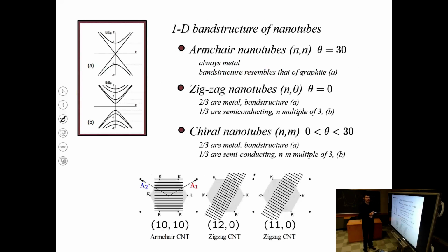So this is the difference in the band structure, what I was trying to explain with these cuts. Each of the cuts gives you a band. You have a two-dimensional graphene band structure. For each of the cuts, you can plot how energy evolves along that cut, and then you can plot them all on top of each other, because in the reduced zone scheme, all the bands will live in the same Brillouin zone. Now we have a one-dimensional Brillouin zone because of this additional quantization condition. We live along these cuts. And when we have 20 cuts, like in this case, that means we have 20 bands. And some of the lower bands are represented here.